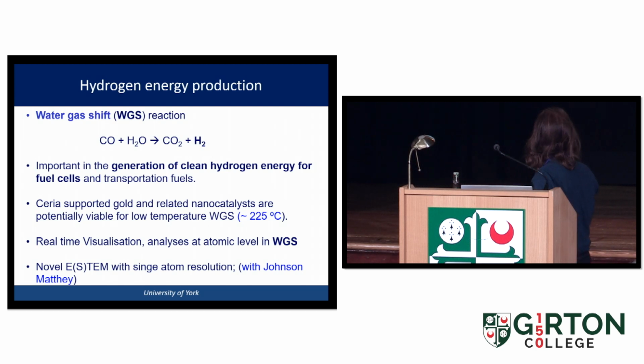Ceria is a very strong support, and so we want to interact with it at 225 degrees C. The lower the temperature, the more economical the process is because you consume less energy. So we want to do real-time visualization and look at the atomic level in this reaction. And for the first time, we can actually see how these gold atoms interact. So we are working with Johnson Matthey on this development.